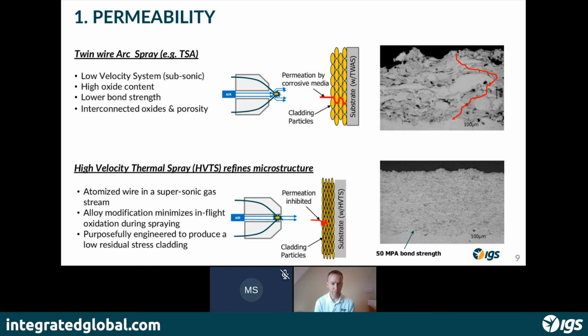Otherwise, even if the alloy is resistant, if it's permeated, then the substrate will corrode underneath and pop off your thermal spray cladding. So IGS, we looked at the processes we had available, a standard or a conventional twin wire arc spray process. So here you've got your two wires coming into the gun. You've got your arcing point outside the gun, and you've got your gas flow hitting that arcing point and then projecting those particulates onto the surface.